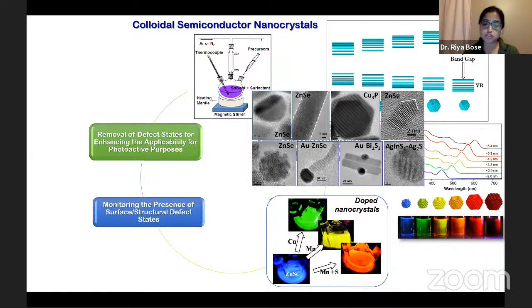As you can see in this picture, we can have blue emitting zinc selenide, and then we can change its composition. Here we mostly change the composition in a way that does not change the band gap, but inserts a certain amount of foreign material into the band gap, creating a state in between the valence band and conduction band. So it can modify the emission from the host nanocrystals. If we dope zinc selenide with copper, we can get green emission. If we dope with manganese, we can get yellow emission, and so on.